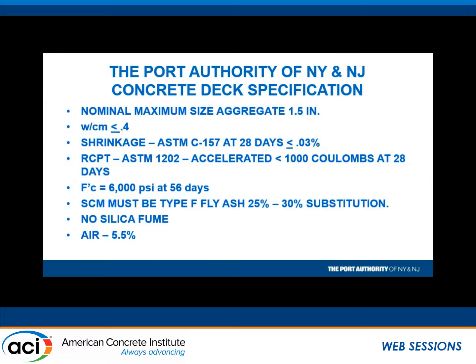One thing we found, even with that, which is stricter than what ASTM has, was that on bridge decks we used to use silica fume, we don't anymore, and we would get a lot of cracking in the silica fume mixes. When we followed this standard, the silica fume, the slag, and the fly ash mixes all exhibited the same shrinkage value. All the same. We said, well, how is this test worth anything? How come in the field there's so much difference, that the silica fume exhibits so much more cracking?